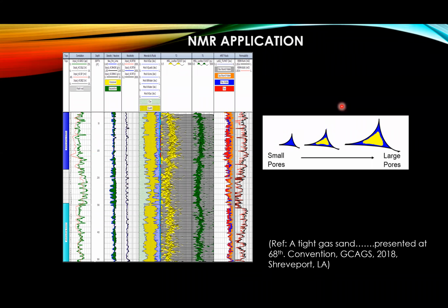Ideally, NMR uses a cutoff value to differentiate between the free and the bound fluid, but that model doesn't work very well, in the sense that sometimes when you're going into the bigger pore here, it will show the whole thing will flow. But we know for sure that there is a bound fluid here, which is the wetting phase, and it's not going to flow. So there's a slightly different model. It's called the spectral BVI model. When you use that application, you can actually take care of this rugosity within the pores and take into account how much is bound versus free in a much better way.